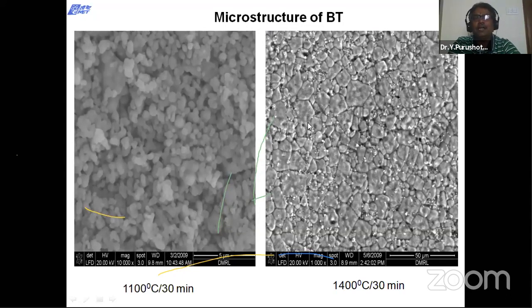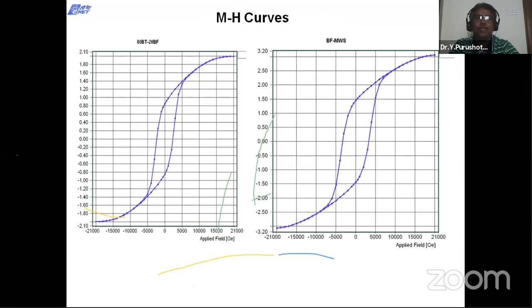So for this kind of academic purpose, we can do sintering at different temperatures and different conditions. And these are the composite materials, barium titanate, barium ferrite, and barium ferrite by microwave sintering. And you see here, this hysteresis loop is very well defined in the microwave sintered samples because magnetic properties are more, saturation is more, and coercivity is also more in these microwave sintered samples.